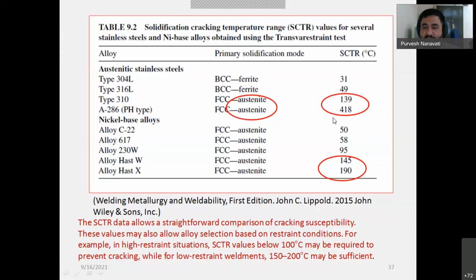So intentionally, I have marked this. Why I have marked this? To show you the higher the solidification range, say 139, 418, there are higher ranges. 144, 145, 190, higher solidification range and higher the susceptibility. This could be seen with, you could see the precipitation hardenable grade A-286, where the primary solidification mode is austenite. It means when you have a combination of both on the second column and third column, when your primary solidification mode is austenite and you have a high solidification temperature range, then your crack is certain. Right? This is the analysis of this table.